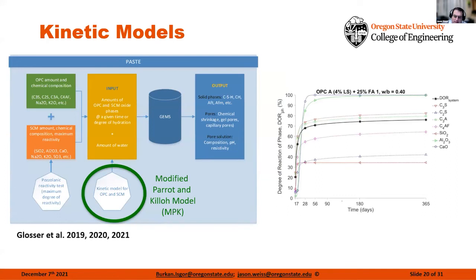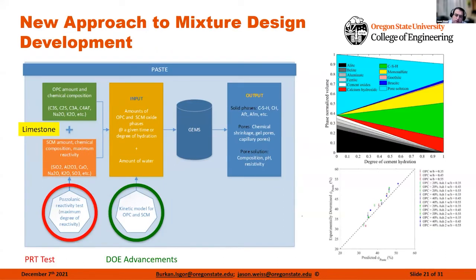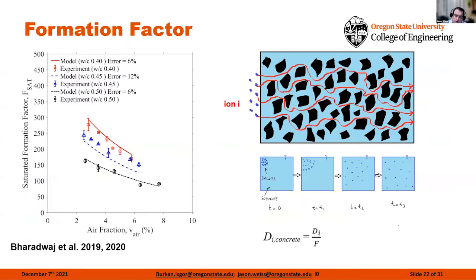We can bring kinetics into this system. We've actually done some work for the Department of Energy to really bring in how we modify these kinetics and have been able to use this to now start predicting things like the overall porosity and starting to bring in things like the formation factor or the tortuosity. Now, one of the things that we've been really trying to explain to people is the transport properties that we're typically measuring, whether it's through electrical resistivity or rapid chloride, have an error when you vacuum saturate those materials.